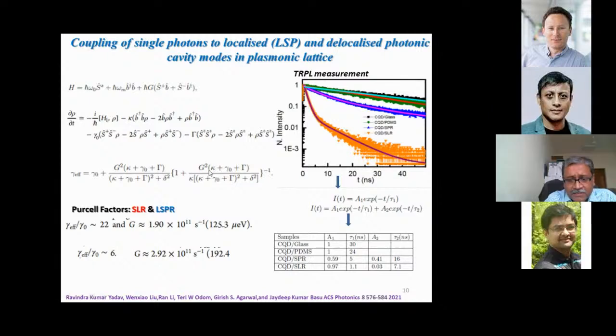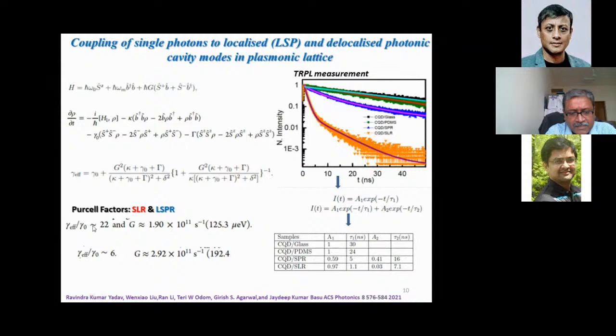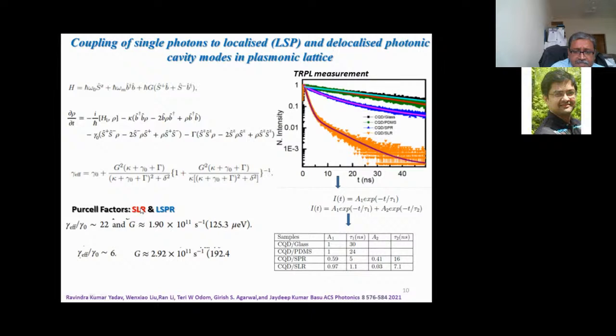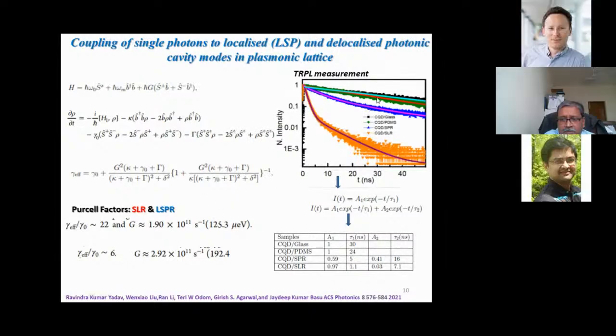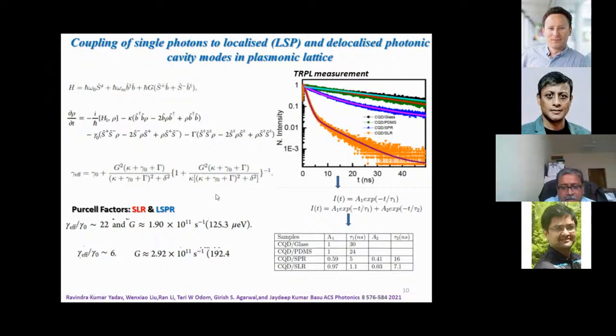This is for the lattice resonance decay constant, or the LSPR decay constant. This is for the emitter in vacuum or free space, and this is the dephasing parameter. With these quantities, one can try to extract, for example, the Purcell factor. You can extract the Purcell factor from this and from this, and you see there is a significant increase in this quantity. This is for only the LSPR mode, and this is for when you have the lattice resonance. So this is something we could pull out by doing this theoretical modeling.